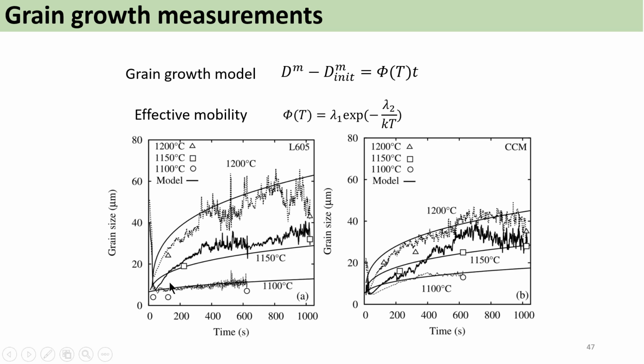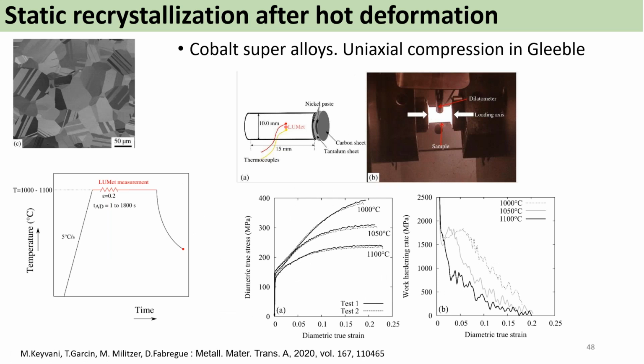So here again, you can see that this Lumet was capable of capturing growth rate in different alloys for these cobalt families. So to go further on those studies, we use this calibration that we are now reassured is operating fine, and we looked at the same type of studies I've showed you earlier on static recrystallization, in which we do an initial deformation at a strain of 20% at a temperature ranging from 1000 to 1100 degrees.